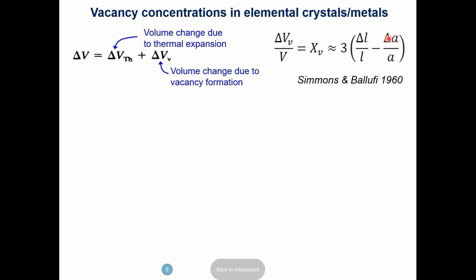If you have ever taken the X-ray diffraction class, as you create defects in your solid, what will happen to your X-ray peak position? It will shift. And from the shift of the peaks in your X-ray diffraction, you can actually estimate delta A, the change in lattice parameter. So there are experimental ways of getting this from X-ray diffraction.